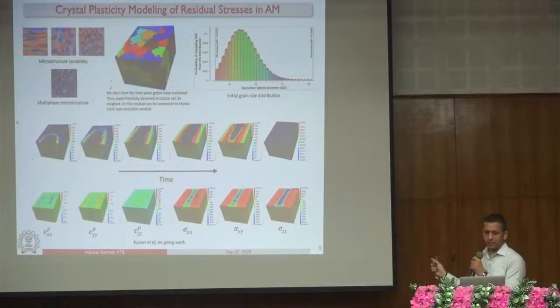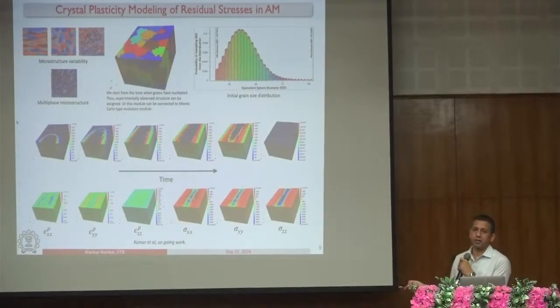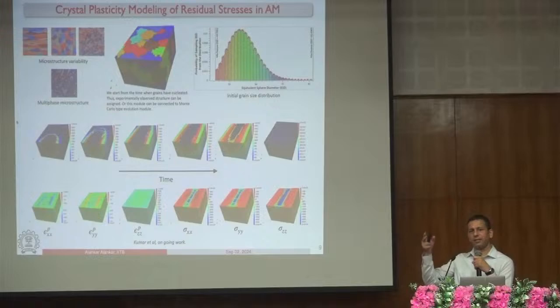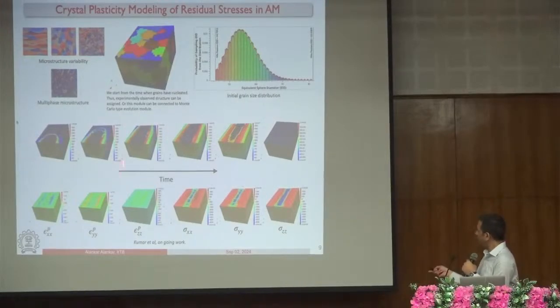This is an example again of crystal plasticity simulating residual stress in Ti-6-4, right? So we do not simulate the complete solidification process. We assume that grains have already nucleated and they are in just solid state, and starting from there, they are trying to squeeze, right? And their dimensions are decreasing, and that's why the residual stress is coming. And by doing this high temperature to low temperature transient simulation in crystal plasticity, we are able to estimate where the stresses will be. The part that you see in blue is a melt pool that we don't simulate. We simulate the nearby area which has solidified, and that is going through phase changes and plasticity, high temperature plasticity. Gives pretty good estimates, right?